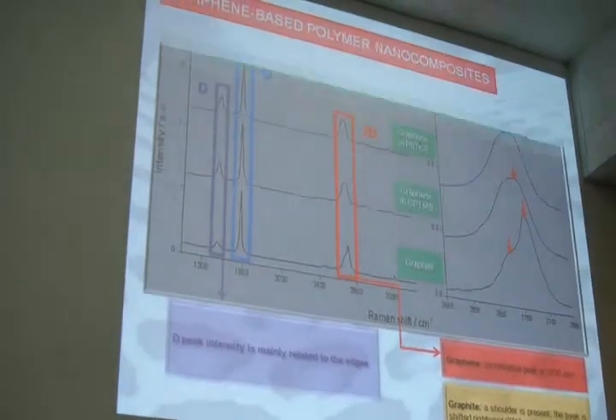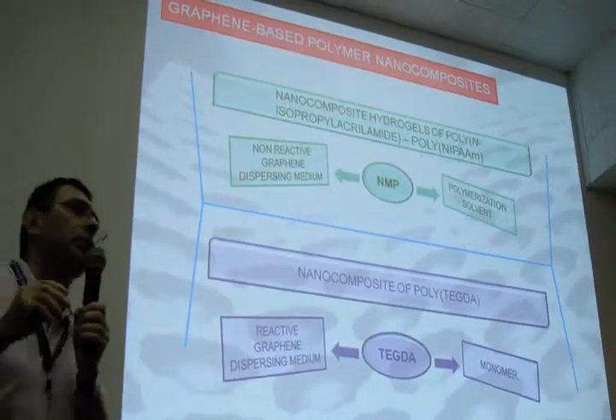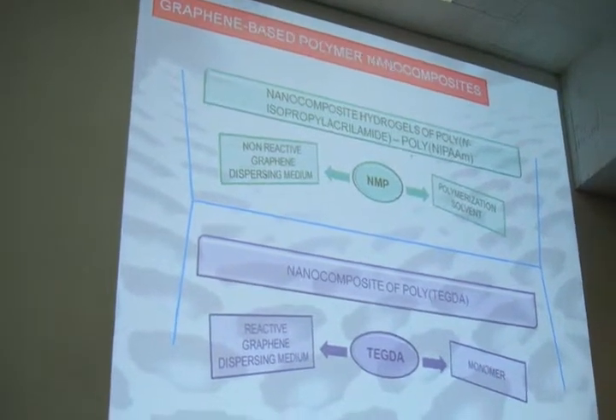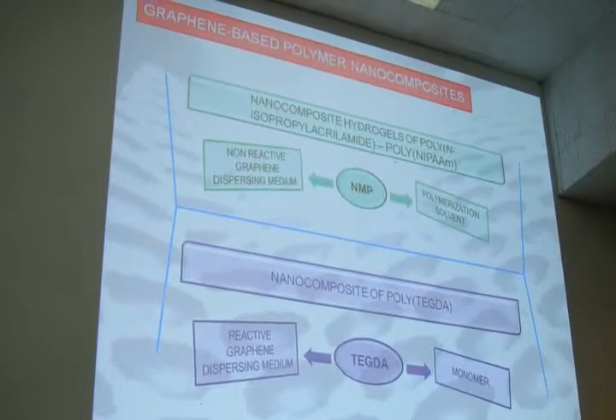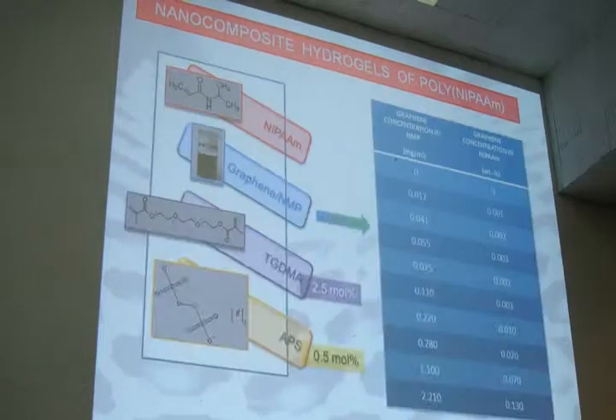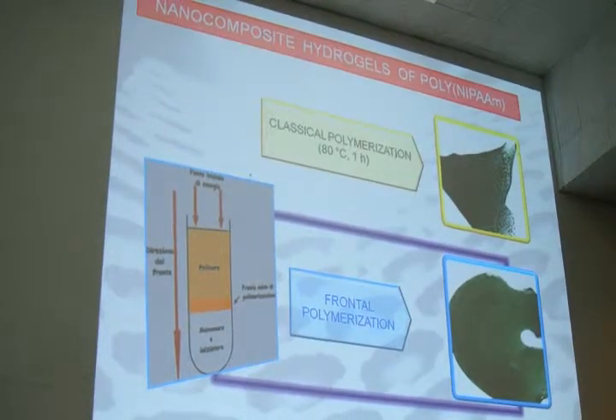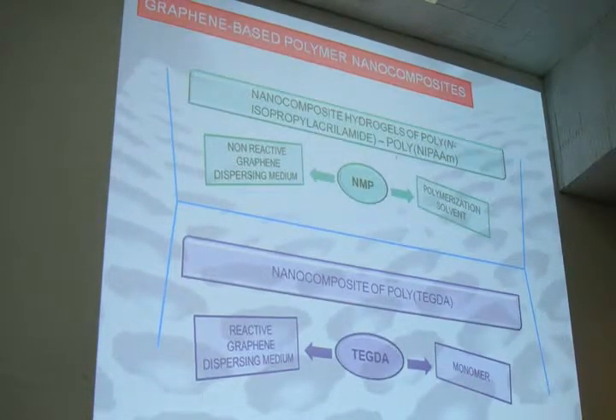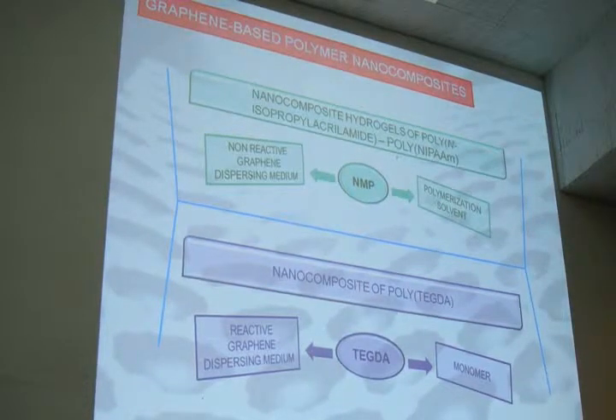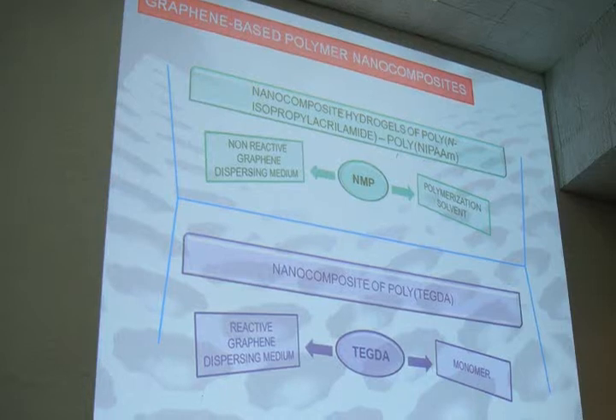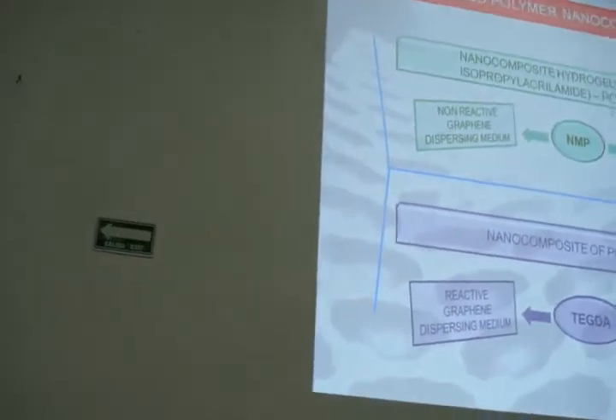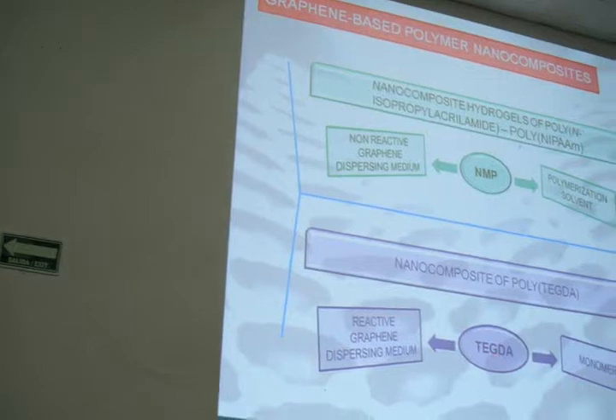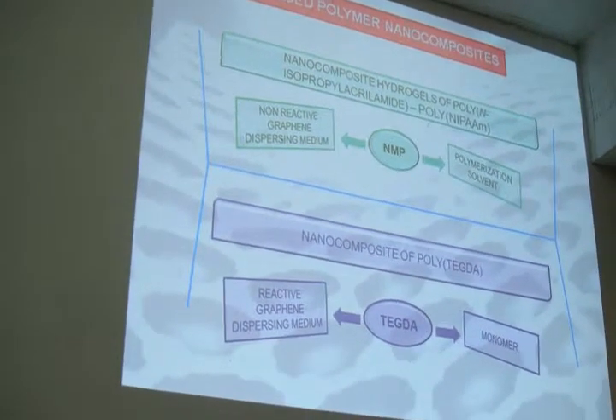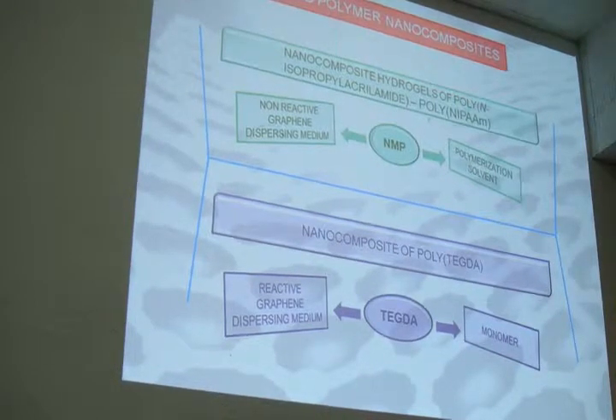Okay, I go a little bit faster. I will just tell you about two examples. I chose these two examples for two different reasons. The first example is by using N-methylpyrrolidone. In this case, the monomer is solid, so it was not possible to use the monomer as a dispersing medium. So we use the solvent and then remove the solvent. And the second example is with the monomer, our best monomer, we can say, tetraethylene glycol diacrylate or TEGDA.